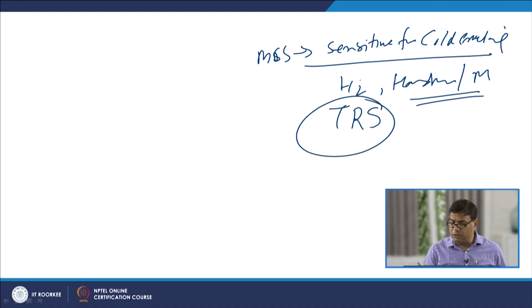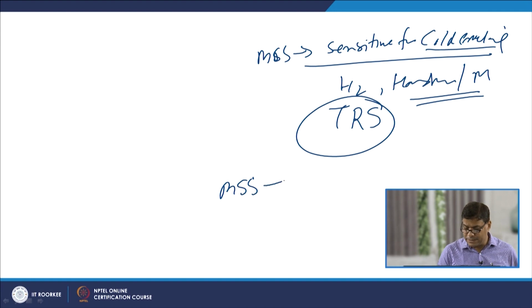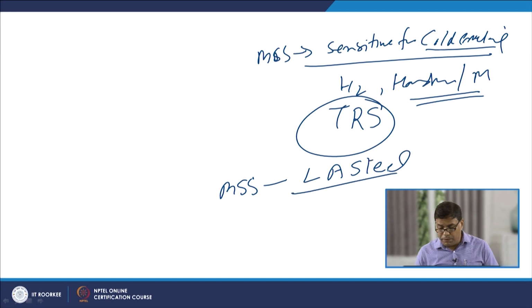So, such a combination promotes cold cracking, and this cold cracking tendency in the case of MSS is similar to that of the low alloy steels. Therefore, to prevent cold cracking in the case of MSS, we will use similar procedures as for the low alloy steels to control the delayed or cold cracking tendency.